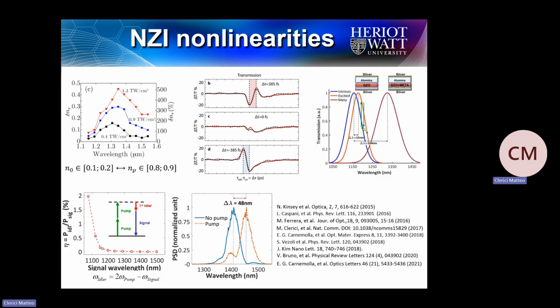This is another work where we exploited the hybrid nature of these materials, and so we took advantage that we can have interband and intraband nonlinearities, and so we can use a two-color excitation. We can pump interband and intraband, inducing opposite changes in the material properties. In this case, you see that the transmittance of the material with one kind of pumping is reduced and with the other one is increased.